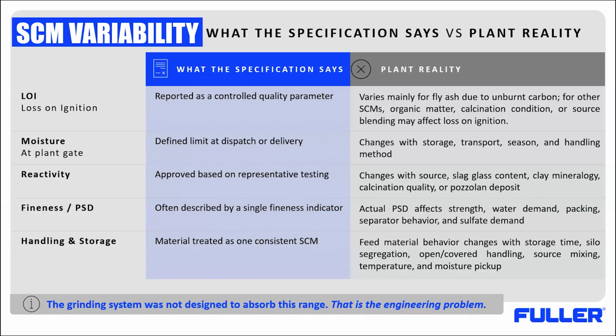Loss on ignition can shift with a source blending or with unburned carbon content, and the moisture can increase during transport or storage. The reactivity can change with slag, clay calcination, or pozzolan mineralogy. The PSD also is very important as it can affect the strength or the separator loading or water and sulfate demand. Even handling and storage matters.